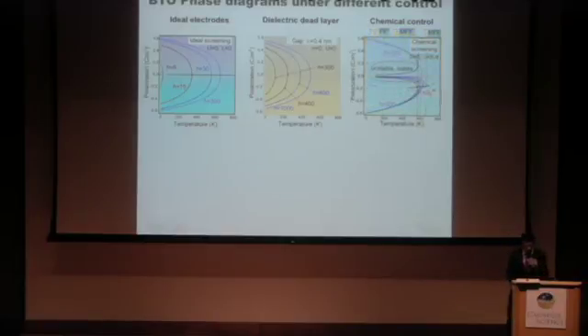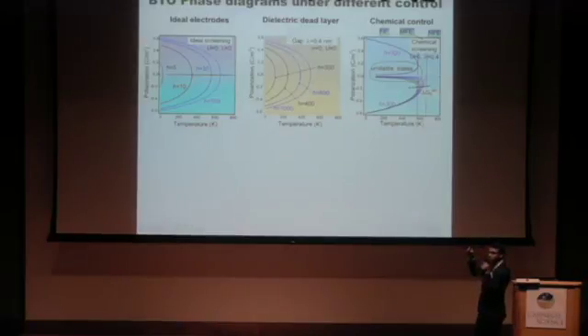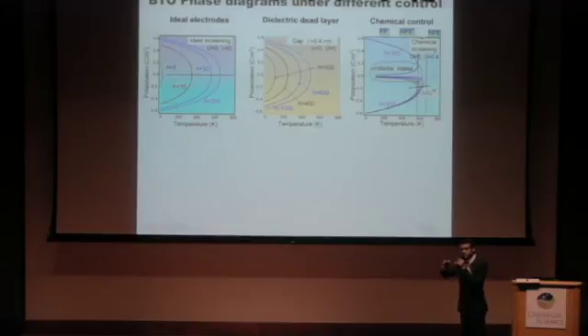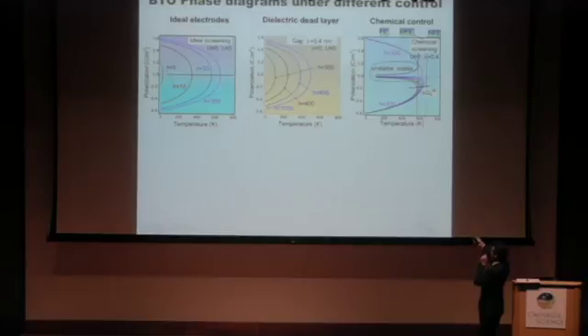Also, if you want to make sure that this is self-consistent, you can do this as a function of thickness, and what you find here is that for thinner films, your region of this mixed state is very large. As you go thicker and thicker, the surface becomes less important, and you find that the width of this mixed region is actually rather small. So this is kind of a sanity check almost. But it's a little bit hard for us to physically change these delta G values. Of course, you can't do that because it's given by nature.